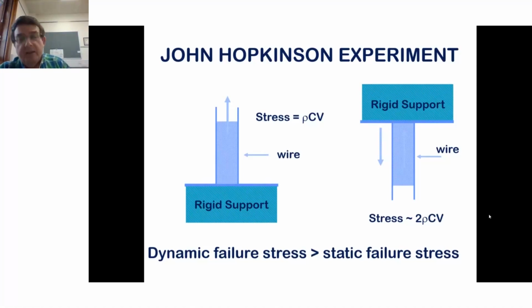When that wave gets to the top of the wire and reflects from the ceiling, it comes back reinforced due to a wave reflection, due to the impedance mismatch at the ceiling. Basically, the ceiling, you hope, doesn't move very much. It's very rigid. That wave comes back reinforced, and the reflected stress is approximately doubled. Not quite 100% doubled, but certainly 99% doubled.